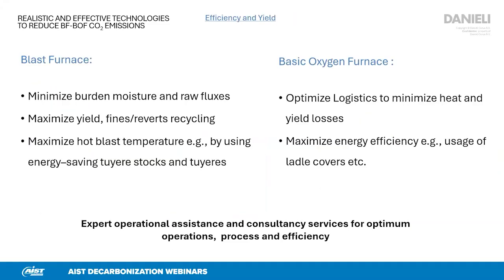Second, right away, the industry can further optimize efficiency and yield of blast furnace iron making and basic oxygen furnace steel making. And some 5 examples that we came across in some steel making companies are summarized on this slide. For example, minimizing the burden moisture and raw fluxes, maximizing the yield and recycling of fines and reverts, maximizing hot blast temperature also by using energy-saving tuyere stocks and tuyeres.